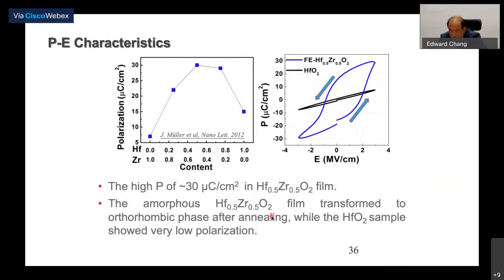The as-deposited hafnium zirconium oxide is amorphous, and you can anneal it, and then it can form this kind of polarization, which is not observed in hafnium oxide alone.